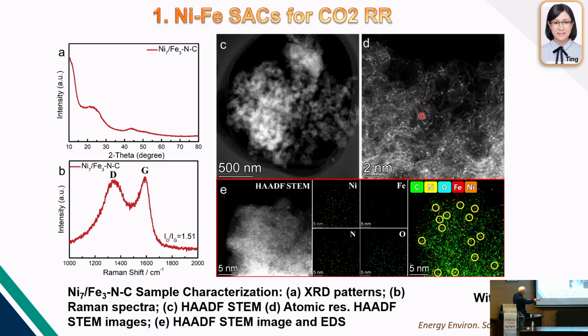So if every one of these spots, by the size and by the brightness, should be a metal atom, then with EDX, you can make a correspondence between what you are getting, if it is iron or nickel or oxygen or nitrogen, and more or less, you can see if there are couples together, like the ones that I'm circling here, when you can find one atom of nickel with one atom of iron.